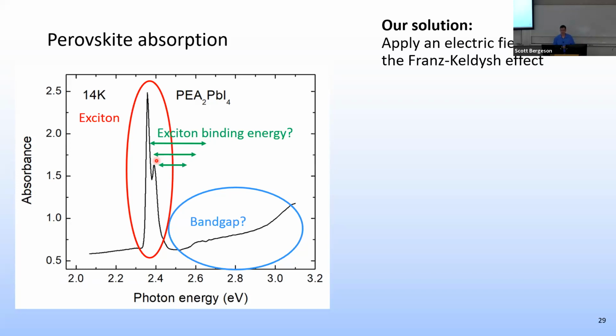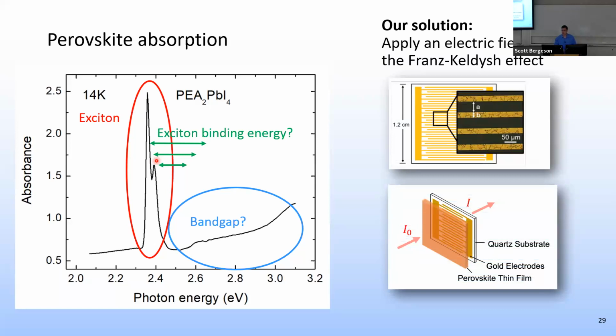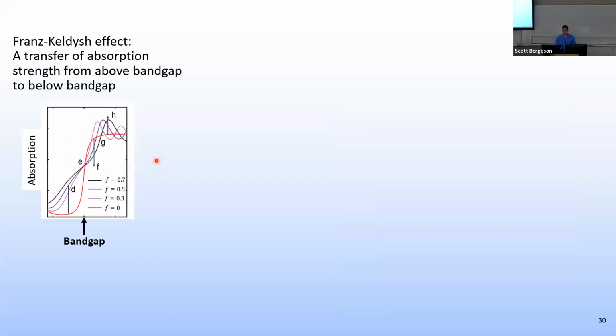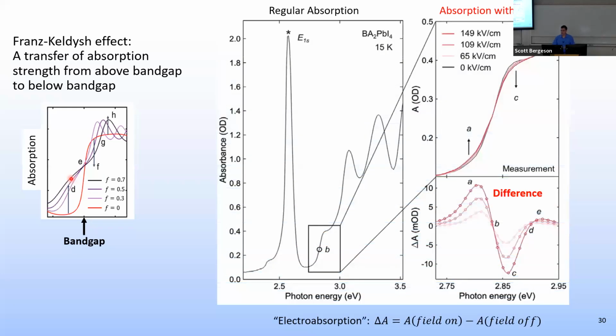And our solution is to apply an electric field and use the Franz-Keldysh effect to figure out what the band gap is. To apply an electric field, we produce our materials on top of interdigitated electrodes. So you've got metal wires really closely spaced, interleaved with each other. And then we apply voltages to these electrodes, which sets up electric fields between the electrodes. And the Franz-Keldysh effect says when you apply an electric field to your semiconductor, you get a transfer of the absorption strength from above the band gap, so this absorption up here, to below the band gap. So you get absorption down here where previously you wouldn't have had absorption. And this is indeed what we see.